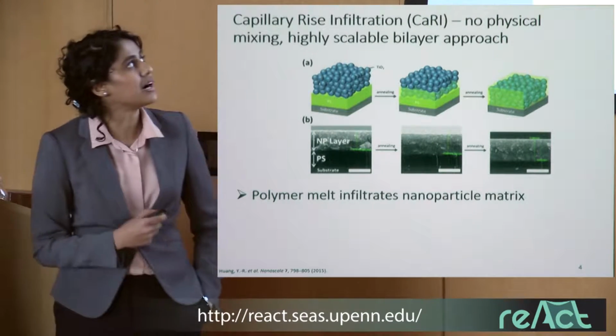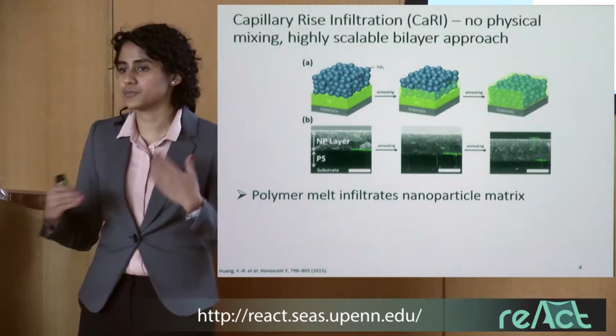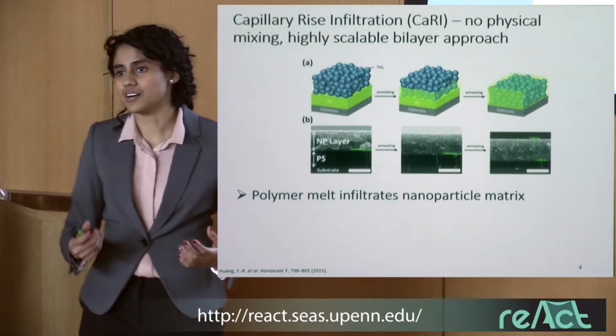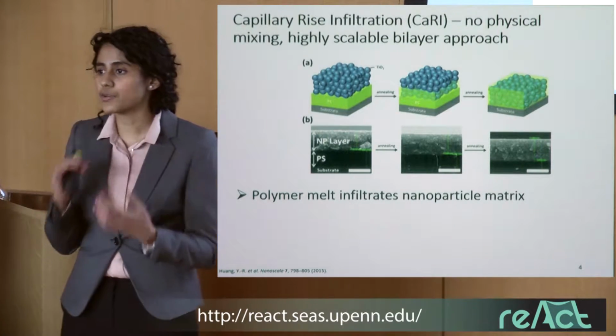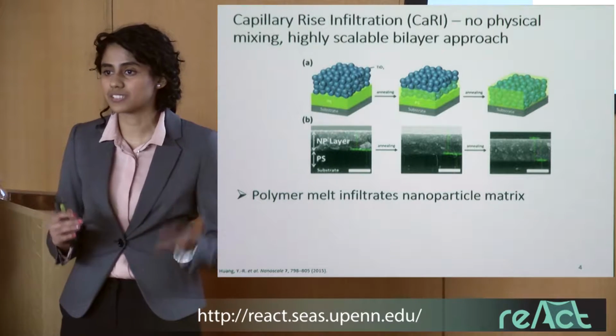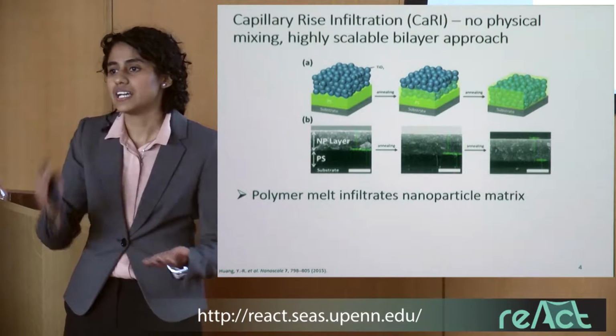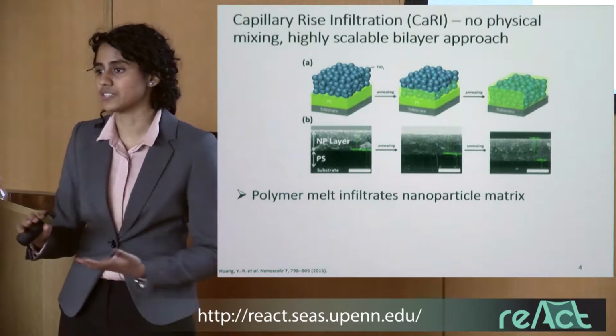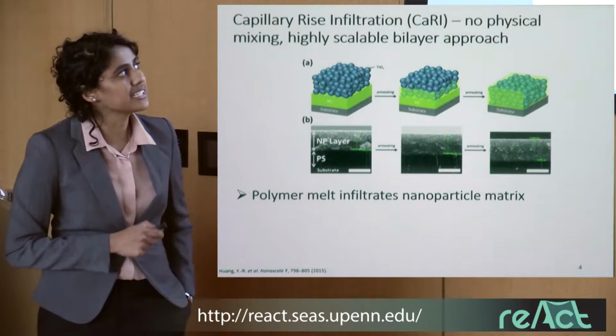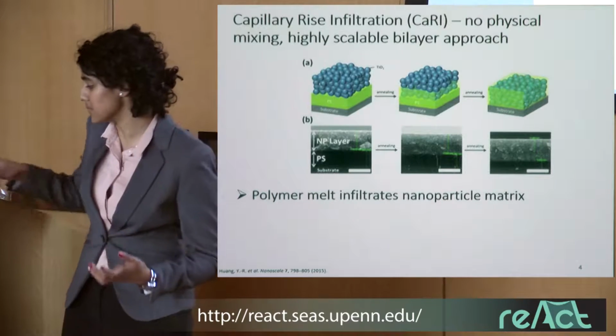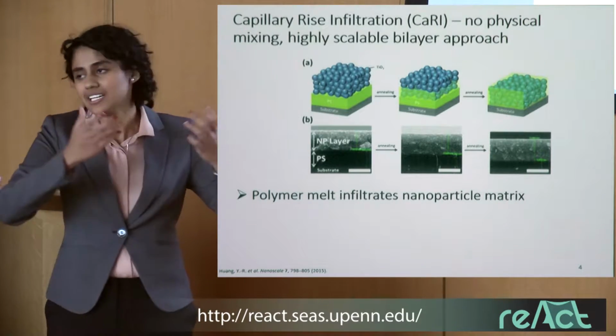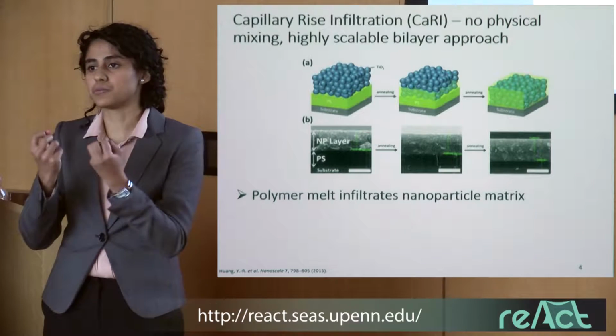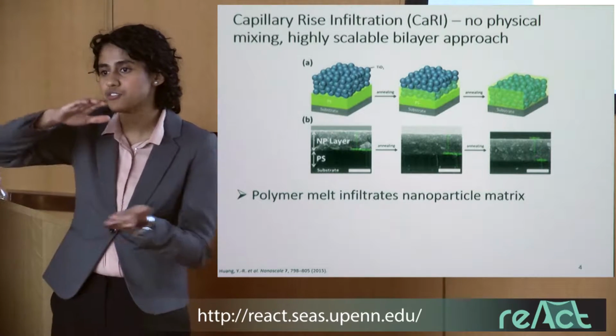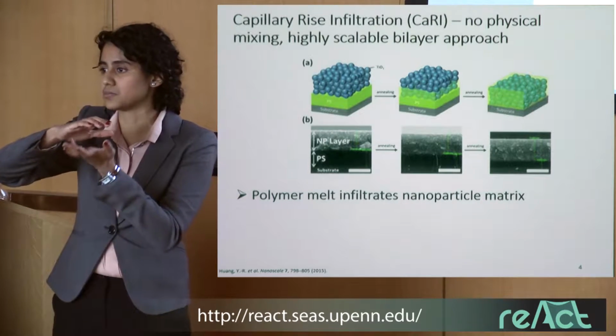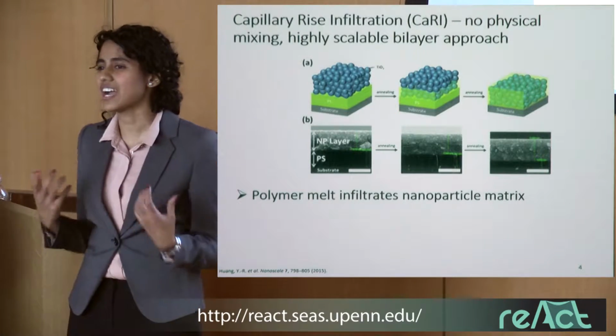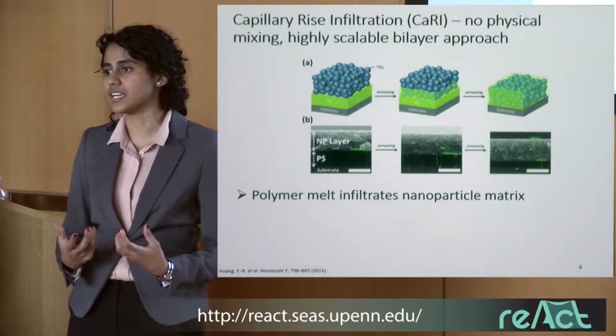Previously in our group, we have been able to circumvent this physical mixing fabrication methodology by coating this bilayer. So basically we start off with a substrate, on top we coat a polymer, and on top of that we coat a nanoparticle thin film. And here we just thermally anneal it, and we're able to see that the polymer infiltrates into the void spaces between the nanoparticle packing, a lot like you would imagine a fluid going into the pores inside of a sponge. And this really makes a very high filler fraction nanocomposite in the end.